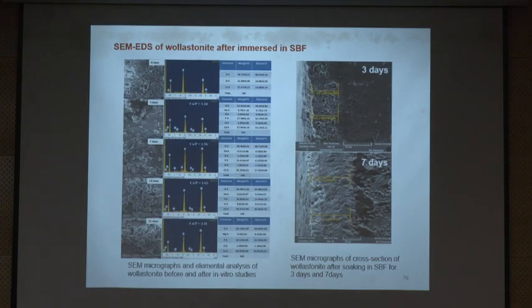And you can see the EDS, right? The elemental analysis. You can see the Ca to P ratio, right? The calcium to phosphate ratio, after immersion. So what is happening there? It is increasing: 1.24, 1.56, 1.63 to 1.62. If you take the bone, the calcium to phosphate ratio of bone will be about 1.66. So you can see here it is almost the same as that of your bone. So that's why we are able to use this material as a bone replacement.